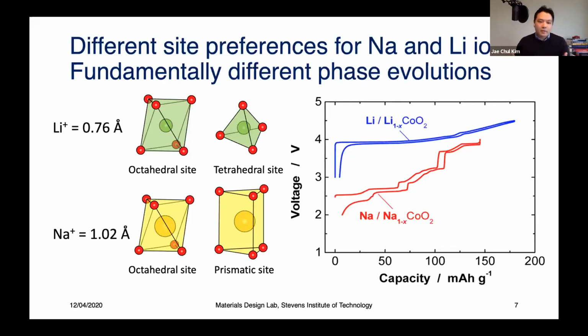So for lithium-ion battery material, lithium tends to sit in octahedral sites, occasionally in tetrahedral sites. But sodium is much larger, so it cannot occupy the smaller tetrahedral sites. It tends to occupy a prismatic site. And this leads to a very complex phase transition upon charging and discharging.